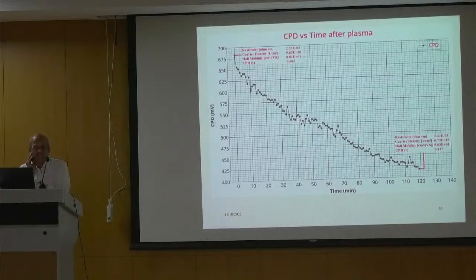What are we trying to do with this experiment? If you have a sample and you expose it to plasma, people say the surface gets modified. It may be cleaned, but surface modification is there. How much modification has taken place, and what are the results quantitatively? Nobody has calculated so far. Because see the beauty of it.